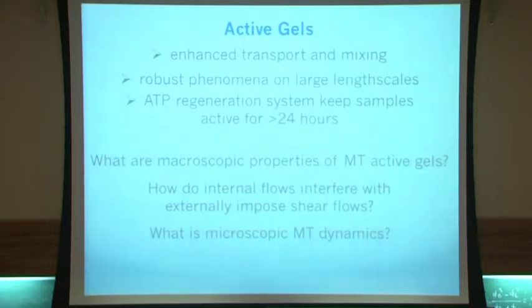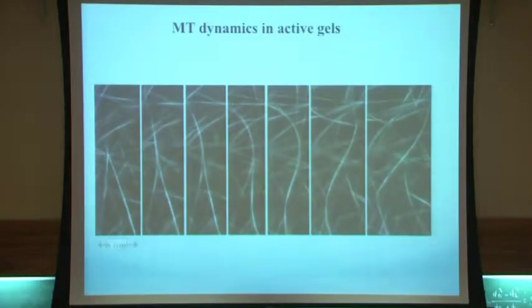So what's actually happening to these bundles? And so here, if you zoom into this active gel, this is what you see, okay? These are your individual bundles now, and this is a time sequence. So you'll see 2 bundles here, and they merge because of the adhesive interactions, the depletion interactions. And as they merge, this merging point increases, right? And as they merge, they are equally likely to have the same polarity or the opposite polarity. If they have the opposite polarity, they'll start extending and polarity sorting.